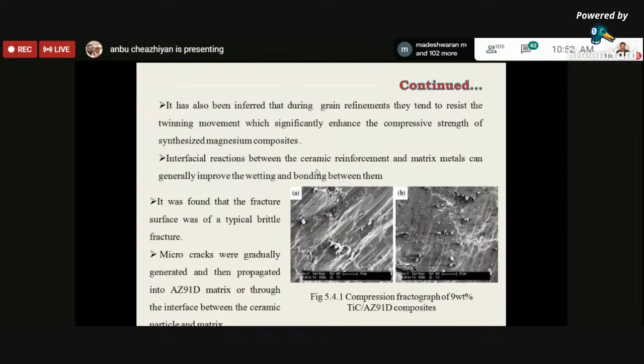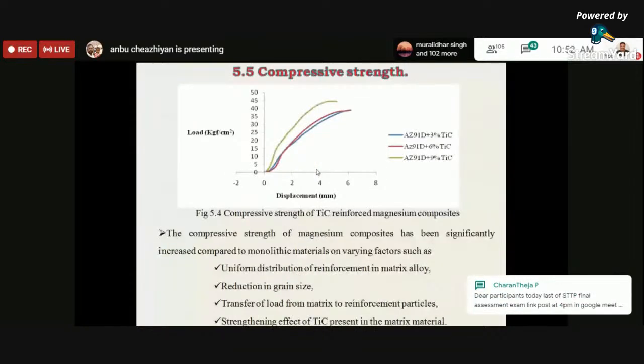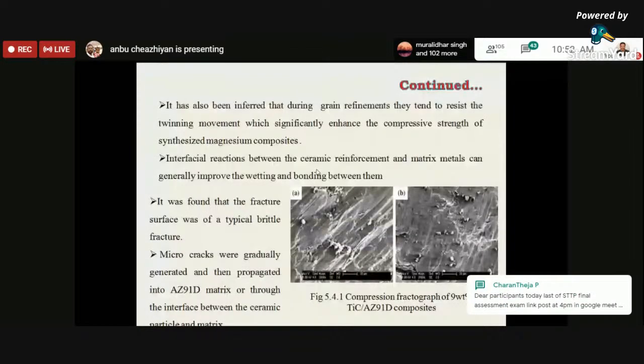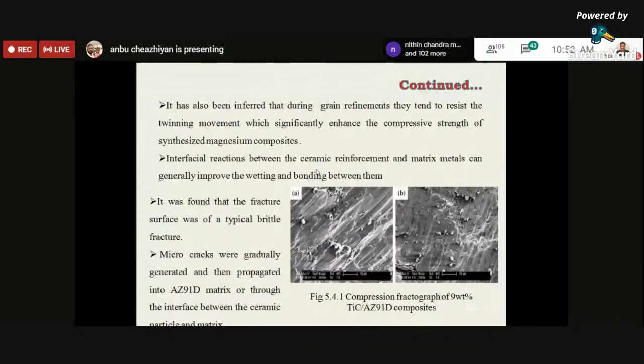It is also noted that the interfacial reaction between the ceramic reinforcement and the matrix metal can generally be improved by wetting and bonding between them. During compression, it has been found that some brittle fractures are raised in the materials. Also, micro cracks are gradually generated and then propagated in the AZ91 matrix throughout the interface between the ceramic reinforcement particles and the matrix.